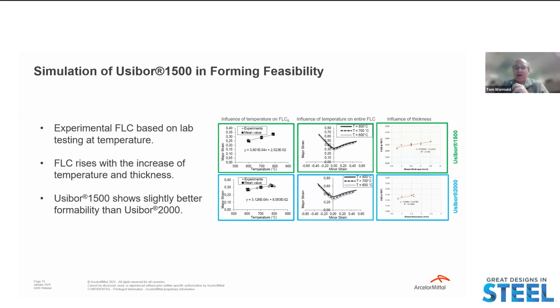In developing the experimental forming limit curves, it's been found that both Usibor grades, the 1500 and the 2000 MPa, show actually quite similar forming limits during stamping.